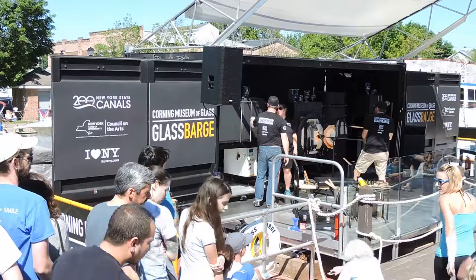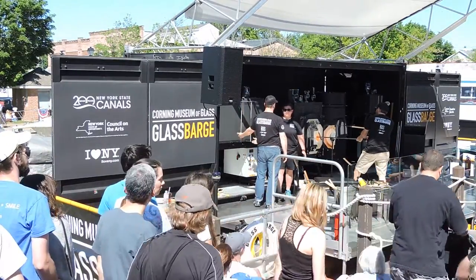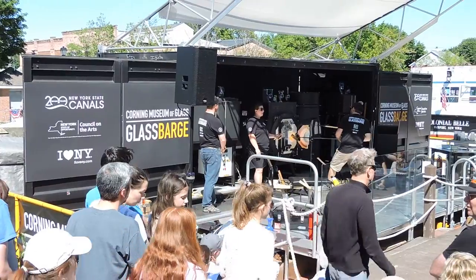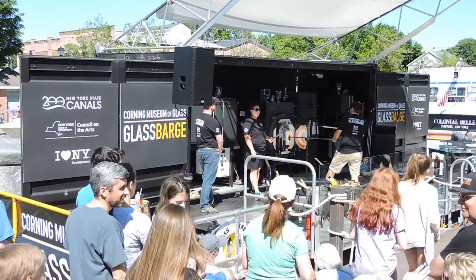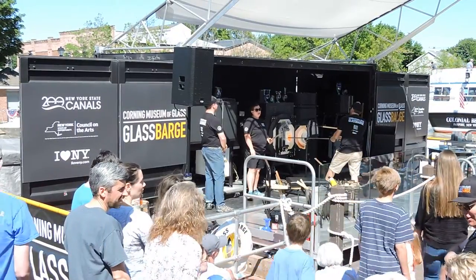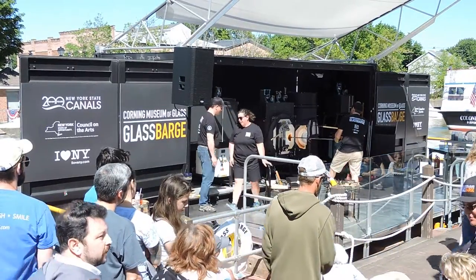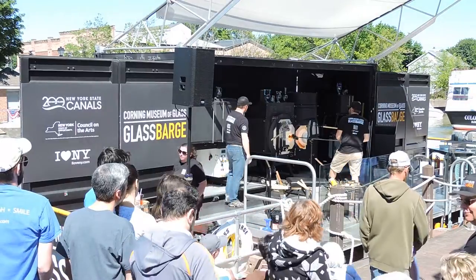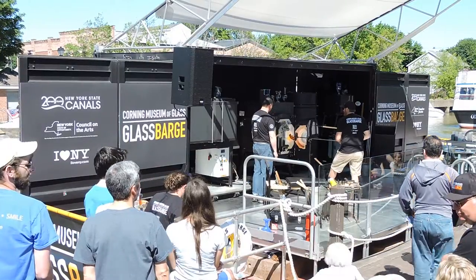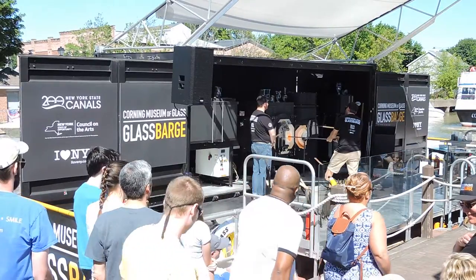Can you see the electrical elements? It's got elements inside — it's like a great big toaster oven for glassblowers. The elements are made of something called molybdenum disilicide. When these elements are cooling, they go through a vulnerable state where they're very brittle at certain temperatures, so they need to cool below a certain temperature threshold. That's why we just turn it down rather than off.